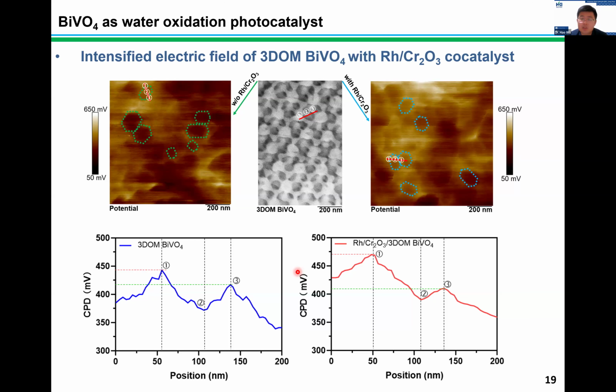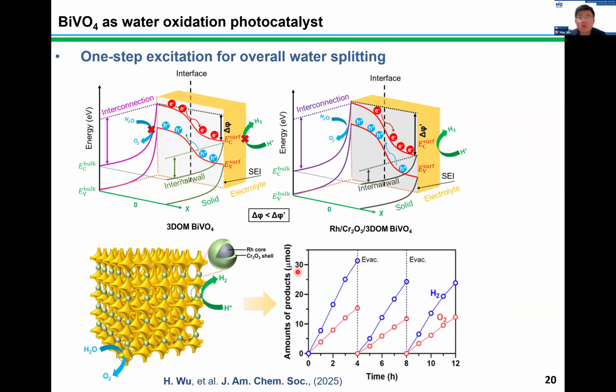And with this optimization of the co-catalyst decoration, we achieved the one-step excitation of bismuth vanadate for overall water splitting with stoichiometric evolution of hydrogen and oxygen. The apparent quantum efficiency is around 0.4%. This is also the first time for us to report that bismuth vanadate can be utilized for simultaneous production of hydrogen and oxygen, which is very meaningful to the community.